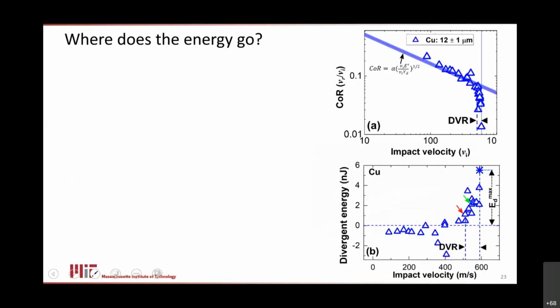All right, so we're starting to get smart here. We can measure the yield strength from the plastic part of this curve. We now understand that this divergence regime is about the onset of a hydrodynamic effect, the formation of a jet. We can now go a little further and try to understand that bonding process, right? So jetting and bonding go together. Well, what is that about? One way that we've thought about this is by looking at the energy budget.